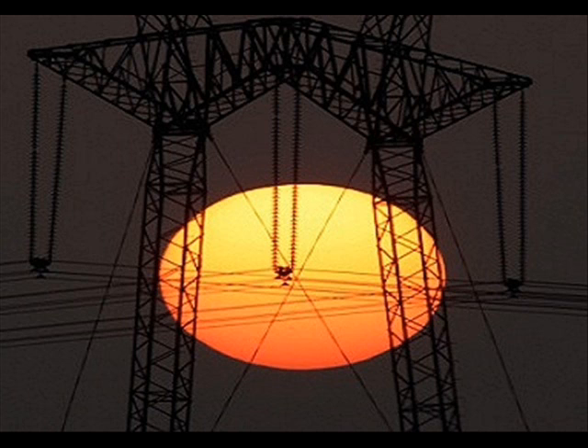More recently, with the advent of computational mineral physics and theoretical means, density functional theory is another way to call it, various groups have been looking for the structure of this high-pressure graphite phase. That's not diamond, that's not graphite, and that is produced just with high pressures. And we were able to successfully verify, confirm what this structure was, just with this set of experiments, and it actually ended up matching very well the structure of this monoclinic structure called M-carbon that was first proposed in 2006 by a group that's led by Artem Oganov, who's now a professor at Stony Brook University in New York.